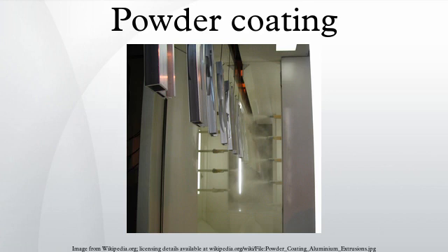Powder application processes. The most common way of applying the powder coating to metal objects is to spray the powder using an electrostatic gun, or corona gun. The gun imparts a positive electric charge to the powder, which is then sprayed towards the grounded object by mechanical or compressed air spraying and then accelerated toward the workpiece by the powerful electrostatic charge.